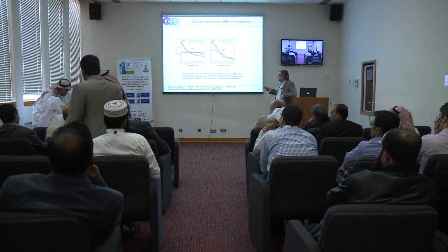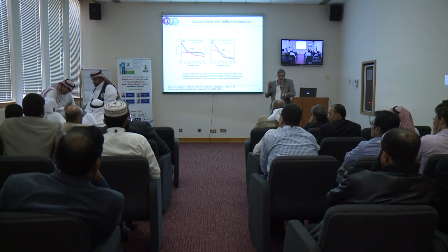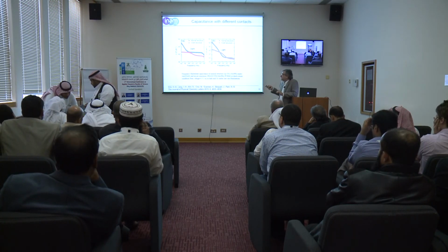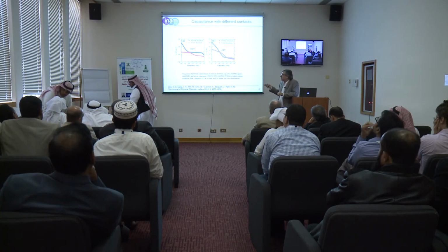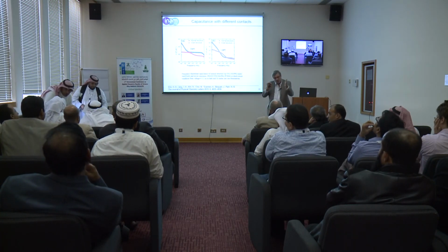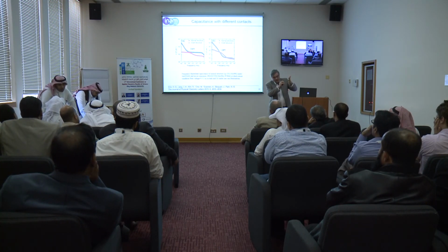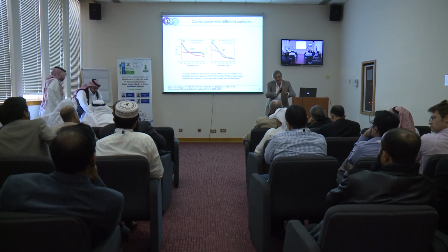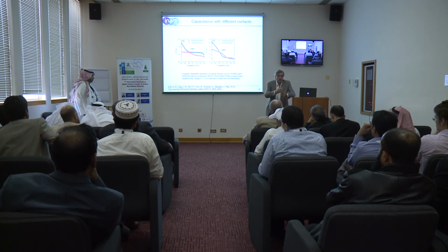As I said before, this low frequency capacitance, we are convinced that it explores the contact. And here the contact is very, very different. For example, in the dark, when you have the TiO2, the ions come to the surface, and then you create a big capacitance, which is this one. When you have fullerene, this does not happen. You don't create these capacitors.